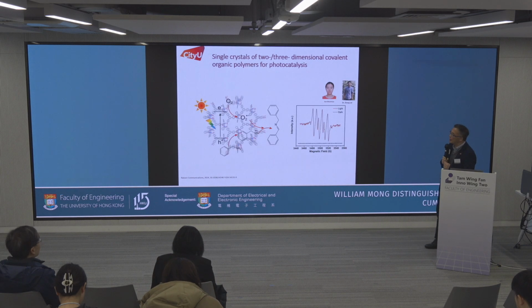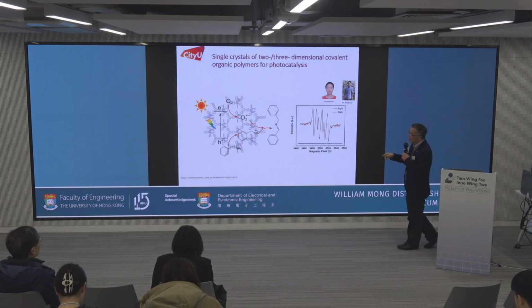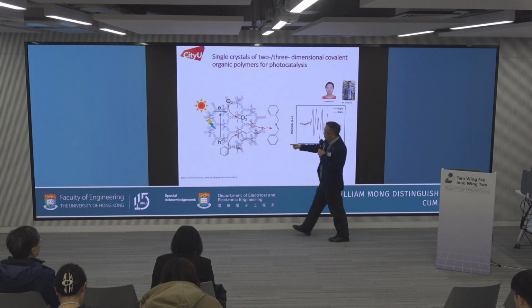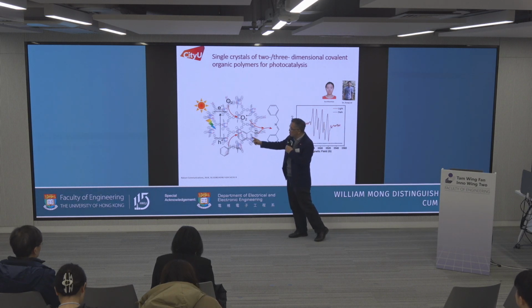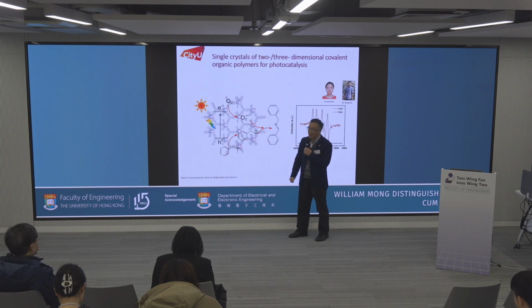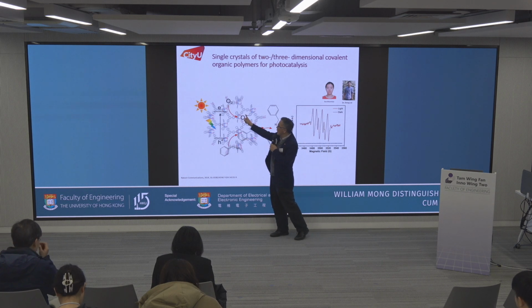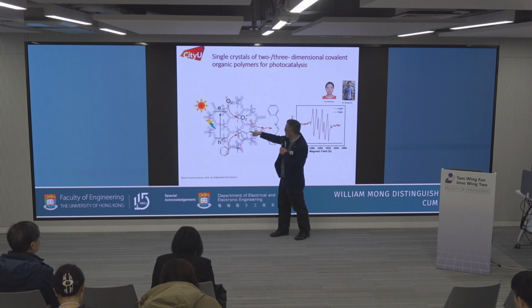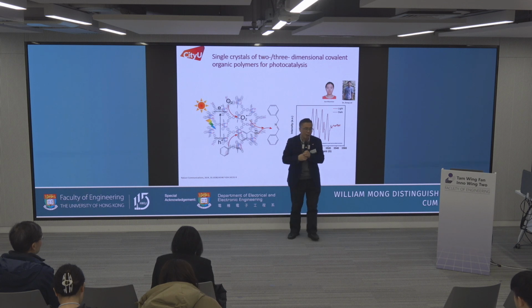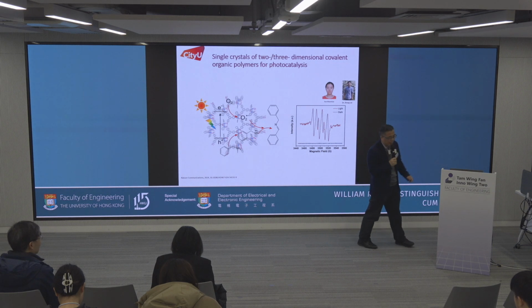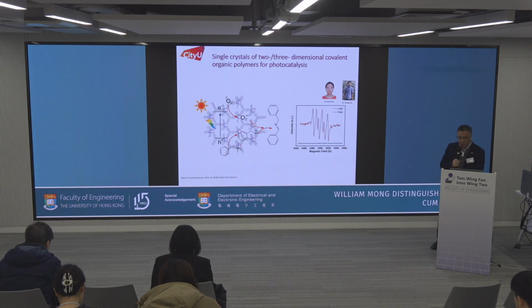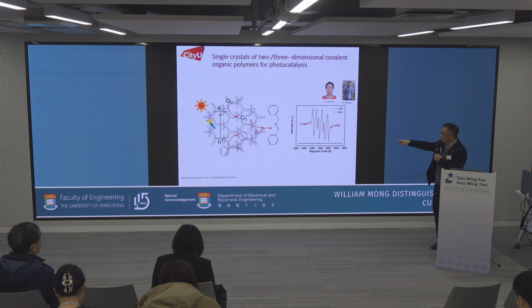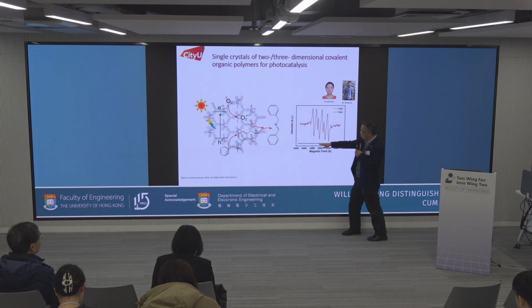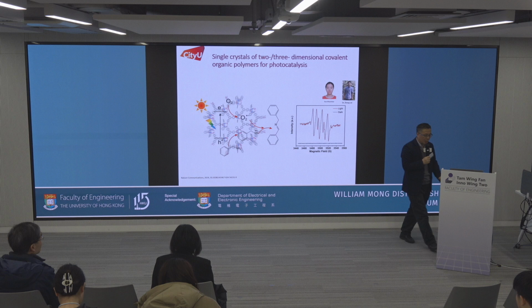And then the mechanism is actually very simple. We shine with light, the electron is excited from the ground state to the excited state, and then the hole can oxidize the amine. At the same time, the electron can reduce the oxygen, and then the oxygen will oxidize the amine again, become aldehyde, and react with the original amine in the system. They can become the imine structure as shown here. So this mechanism is a radical mechanism. Without shining light, the whole material has no radicals. However, shine with light, you can see the radical as shown here.